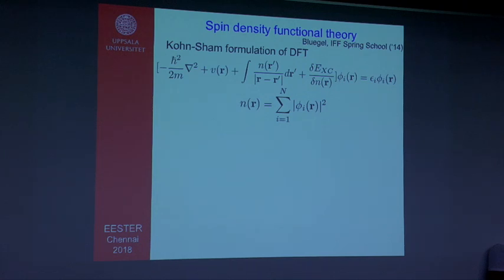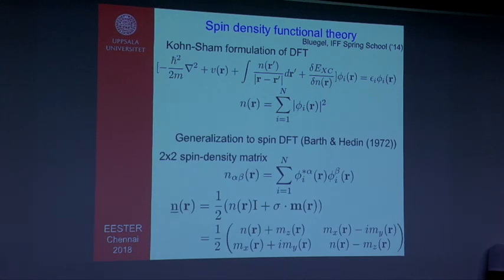The important thing, if you want to do a spin polarized system, you need to extend this idea. And this generalization to spin density functional theory was done by von Barth and Hedin. The same Hedin who did the GW theory. So what was done is rather straightforward actually. The density, which is a scalar variable here, if you want to consider spin density functional theory, a general theory requires a 2x2 spin density matrix. So this is a 2x2 spin density matrix in terms of these single particle orbitals, but now they have these indices alpha and beta, meaning the up or down spins.